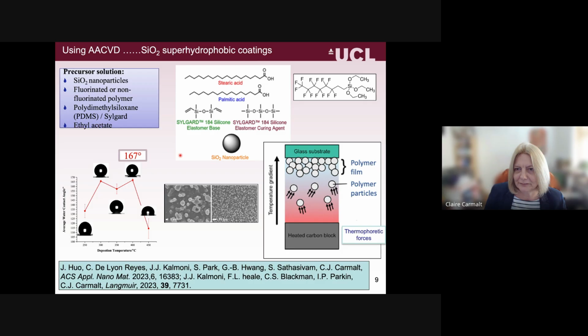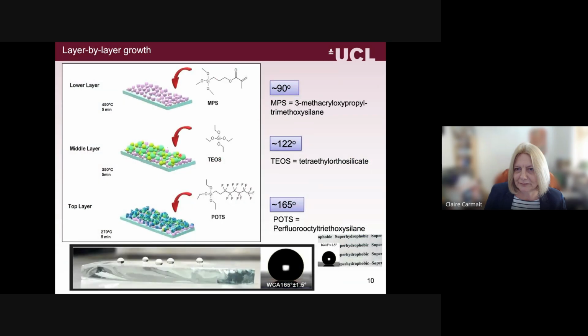So the adherence was good, but it still needed improvement, and the transparency was quite good, but again, not quite as high as we'd want, as it needs to be over 80%. So we looked at some alternative methods for producing this, and one was to think about doing shorter depositions. So an AACVD experiment typically takes between 20 and 60 minutes. And what we thought was if we could go down and reduce the deposition time, we could then potentially get much thinner films. But if we just do it in one pot like normal, then potentially we wouldn't actually get the hydrophobicity that we wanted. So instead we built it up layer by layer.